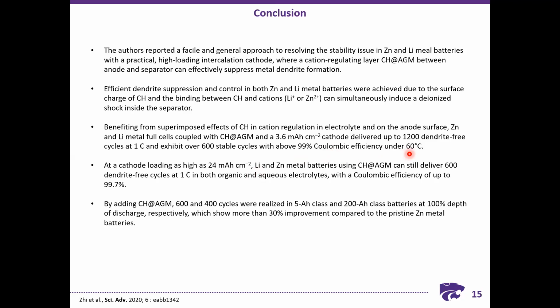Even with a very high capacity, they were able to deliver 600 cycles in both lithium and zinc metal batteries, with a coulombic efficiency of 99.7%. They even went ahead to form commercial level batteries for zinc metal batteries with 100% depth of discharge, and it showed around 30% improvement when compared to the pristine zinc metal batteries.